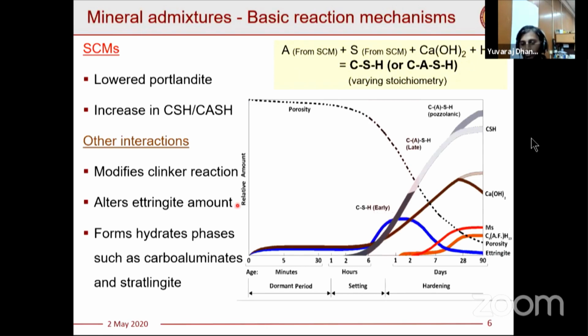For instance, addition of SCM can modify the reaction rates of the clinker phases. It can do some tweaking to the amount of ettringite which is precipitated in your cement systems. And there are other hydrate phases which can start forming, such as carboaluminates or stratlingite, which can have an impact on your performance. So this part of the interaction is most widely talked about. So in this presentation, what I'll try to do is give a major focus on what are the other impacts of the SCM onto the main hydration period in terms of other interactions.